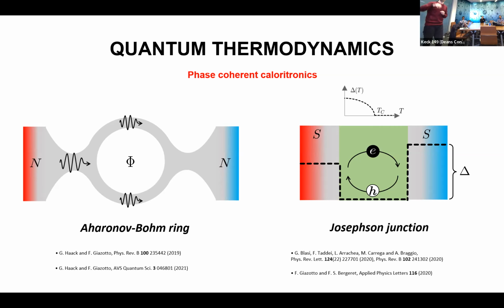And on the other side, we have also the so-called Josephson junctions, which instead are hybrid systems in which superconducting components are put in contact with other materials. In the first case, in the case of Aharonov-Bohm rings, it has been shown in literature, for example, in these last two papers by Geraldine and Francesco Giazzotto, that by applying an external magnetic field, you can control indeed the phase of electrons scattering inside the ring.